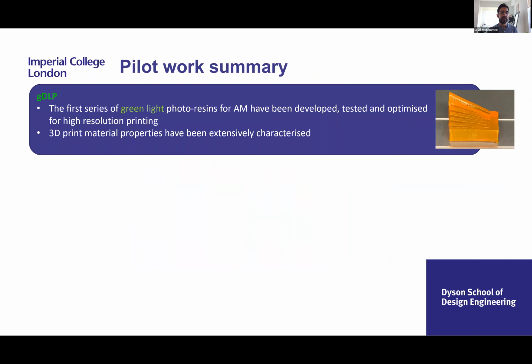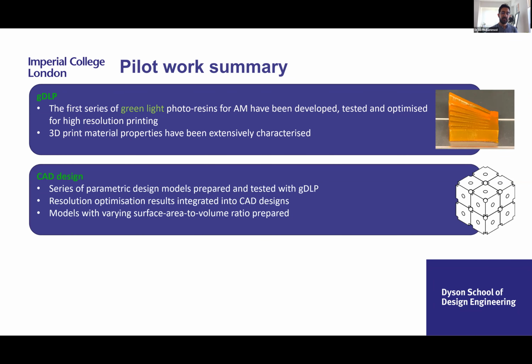The first series of green light photoresins for AM have been developed, tested, and optimized for high resolution. The 3D printed material properties have been extensively characterized. In terms of CAD designs, a series of parametric design models were prepared and tested with the g-DLP. Taking the results from there, the resolution optimization results were integrated back into the designs so that we ensure no failures in the design and that we have the exact measurements and resolutions that are printable in our designs.